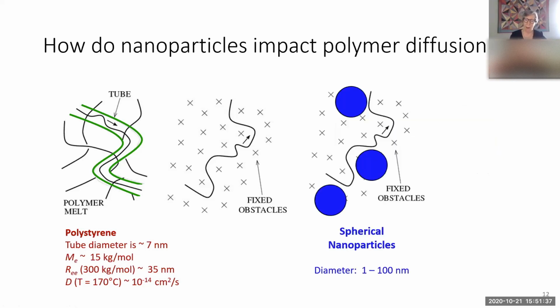So if we want to think about how nanoparticles impact polymer diffusion, there's the schematic, right? There will still be polymer entanglements. The local entanglement morphology or chain conformations might be distorted by the particles, but there will still be entanglements. And then the other thing that makes the nanocomposite situation a little extra complicated is that if you have randomly distributed nanoparticles, locally, they're not all the same distance apart, right? That's what random means. So sometimes particles are a little closer together, sometimes they're a little further apart. So there's inherently a diversity of local environments for the polymer chain to move through, right? And as I said, we're going to be looking at particles that are on the same length scale as the polymer and the tube diameter.